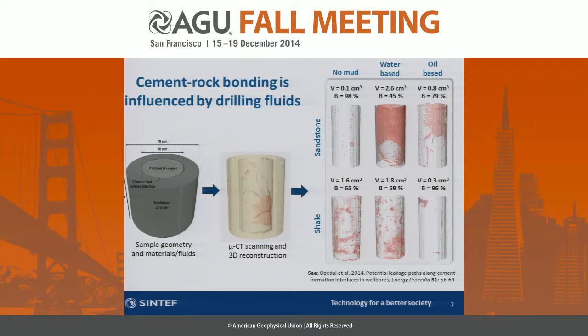And this is relatively interesting because in Norway, the use of the oil-based mud is restricted because they're afraid of leakage of the hydraulics when you're drilling the well. But what you see here is that the oil-based mud is actually giving the best bonding compared to the water-based mud, both for a sandstone and a shale sample. And the V here is the volume of the flow paths, while the B is the bonding percentage. So it's the percentage of the cement surface that is in direct contact with rock. So if it's 100%, then you have perfect bonding. And then the more interface pores you have, the lower the bonding percentage.